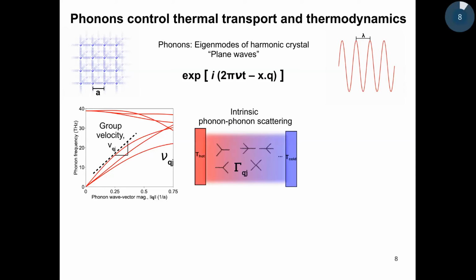So these phonons in a real material also undergo interactions among themselves because no real material is perfectly harmonic, and they always have some inherent perturbative anharmonicities which drive these phonon-phonon scattering processes. These phonon-phonon scattering processes can occur among 3 phonons at a time or 4 phonons at a time and so on. And a net total of all of these scattering processes can be summed up to give a single quantity gamma, which is the total scattering rate.